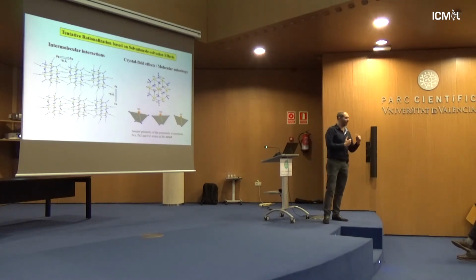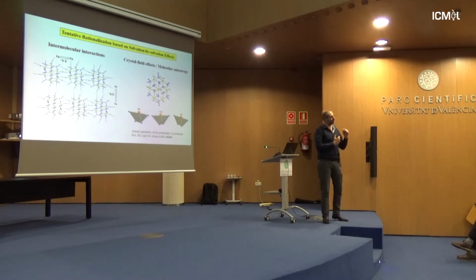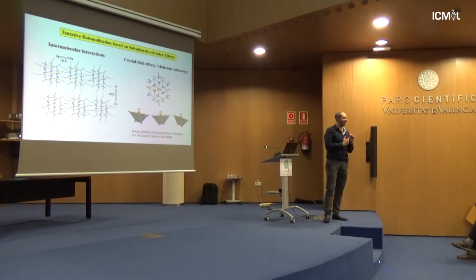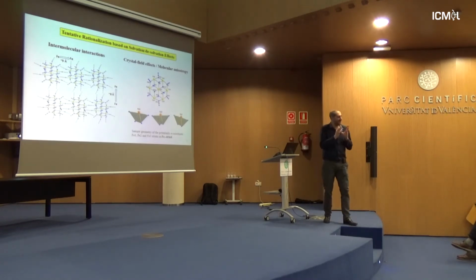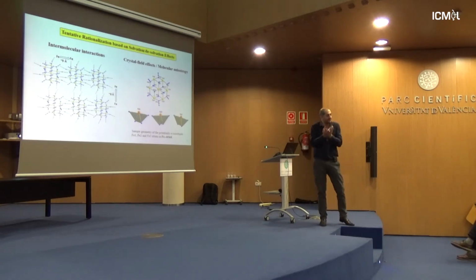It was Jeffrey Long 2 years ago who published a paper saying that iron 2+ centers, single-ion magnets, with a seesaw geometry have an order of magnitude larger magnetic anisotropy than the octahedron. So that could be another hypothetical reason why the dried compound shows that second higher temperature relaxation process.